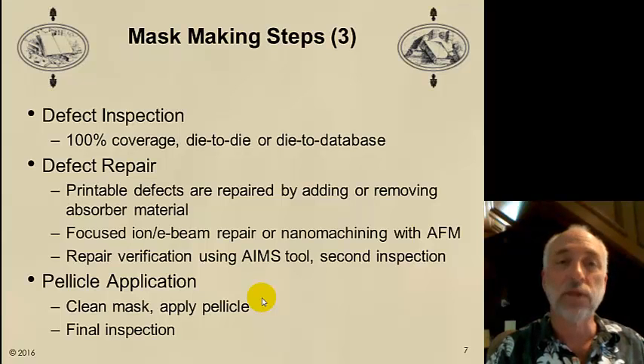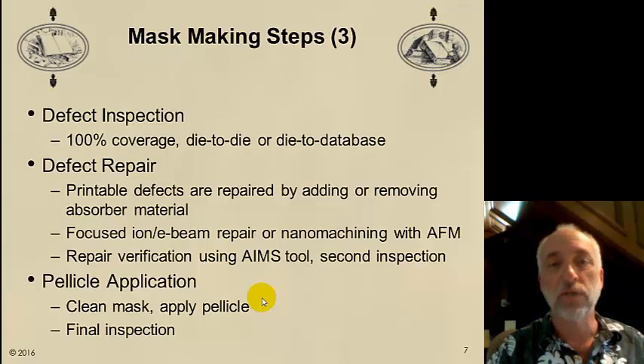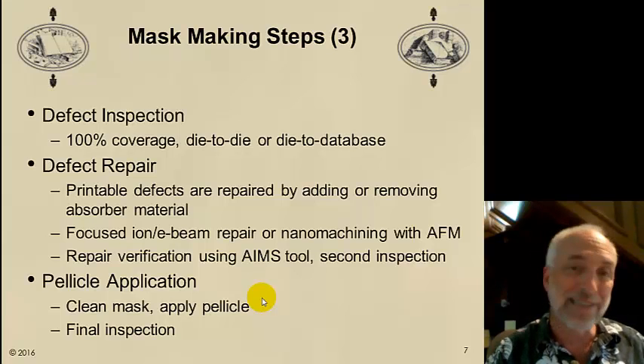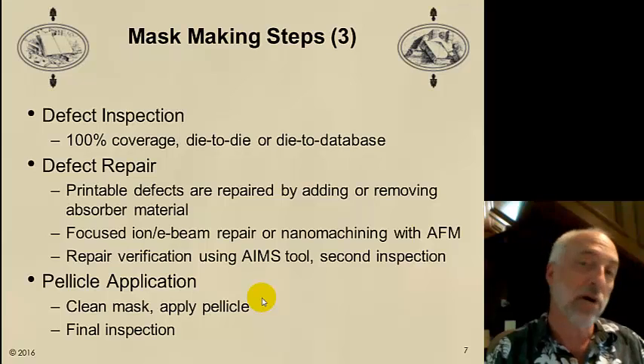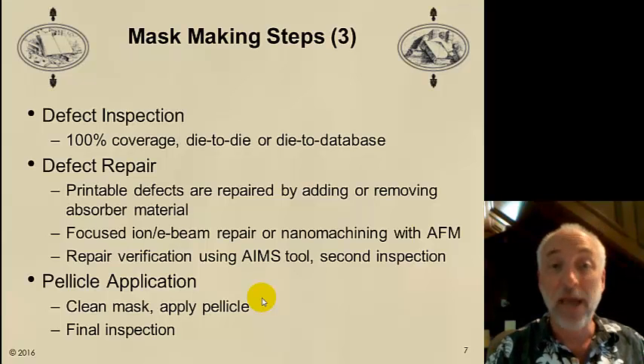We do that with a 100% coverage defect inspection. We do this either die to die or die to database. Remember that most of our masks have more than one chip, more than one die on it. The picture we saw had 6 before. So we can compare an inspection image of one die to an inspection image of a different die to see if there's any differences. Those differences we would call a defect.